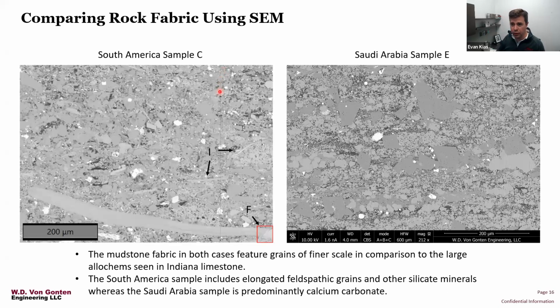Taking a closer look at the Vaca Muerta sample, you can see a lot of silicate minerals. There are elongated feldspathic grains shown here at F, and also this undeniable behemoth of a grain here. In comparison, the Saudi mudstone shows larger dolomitic euhedral crystals, along with more amorphous calcite and smaller calcite minerals. But in both cases, these are all set against the backdrop of this darker organic material.